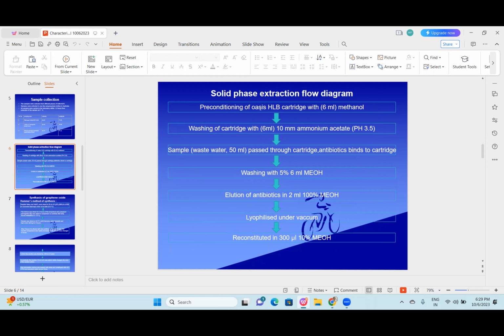First of all, we precondition the Oasis HLB cartridge with 6 ml of methanol, and next step is washing of cartridge with 6 ml of 10 millimolar ammonium acetate with pH 3.5, and after washing, we pass 50 ml of wastewater through cartridge, and the antibiotics present in the sample bind to the cartridge. After passing the sample, we wash the column with 5% methanol, and after washing, we elute the antibiotics in 2 ml of 100% methanol.